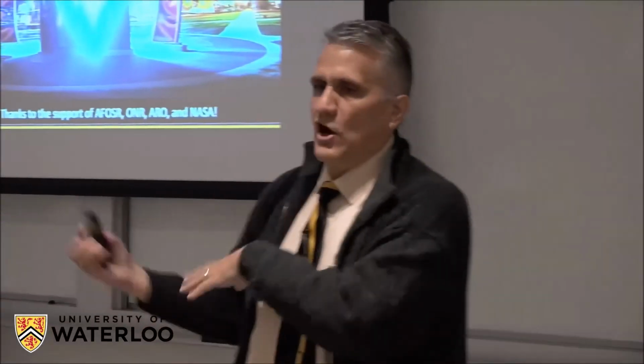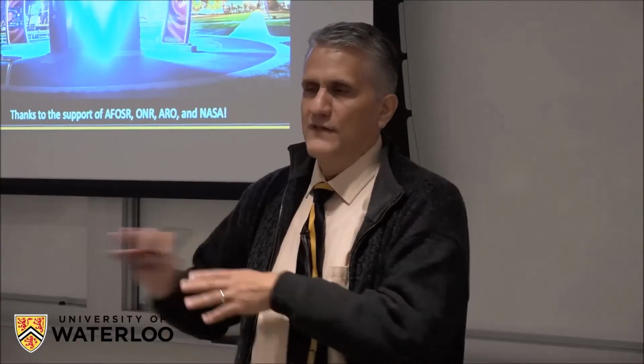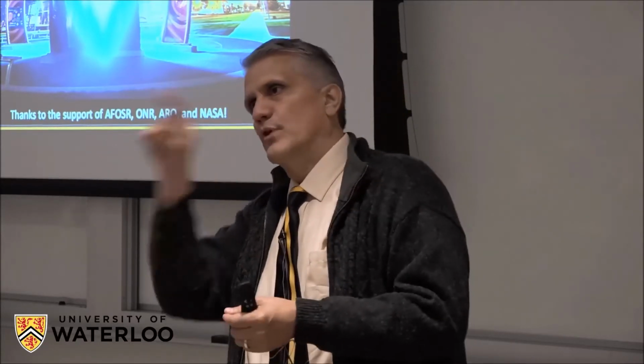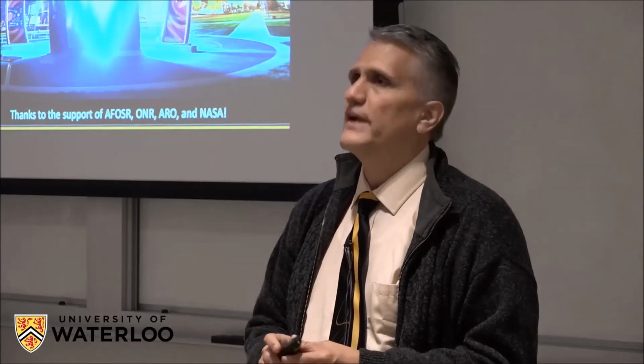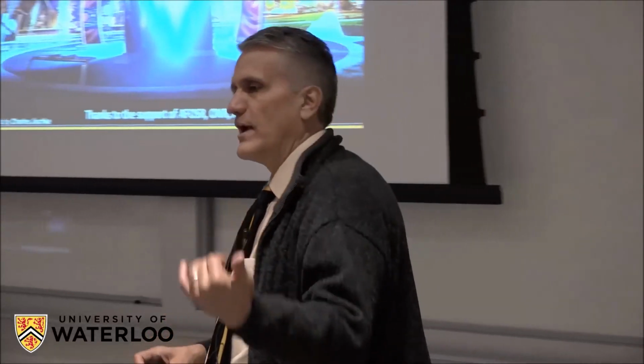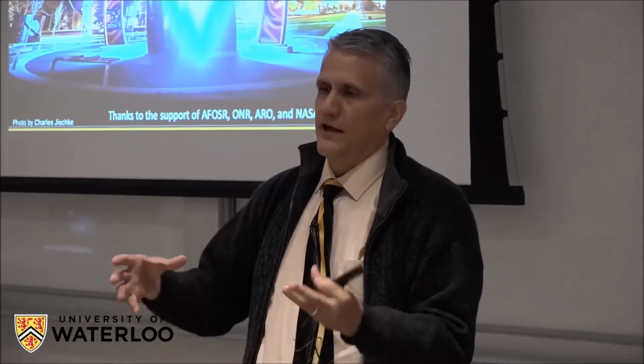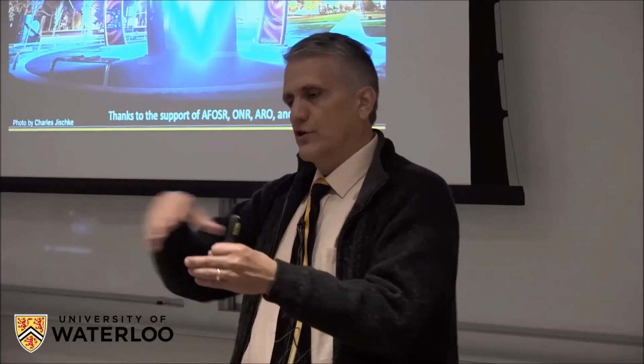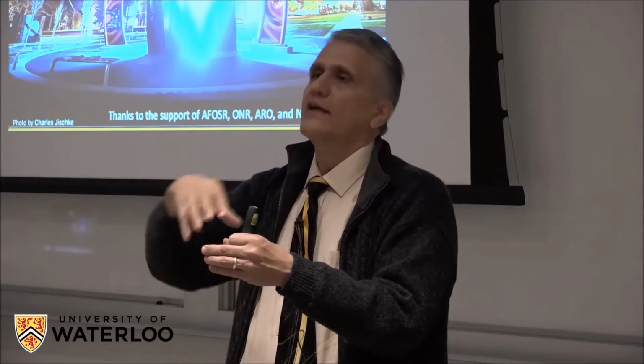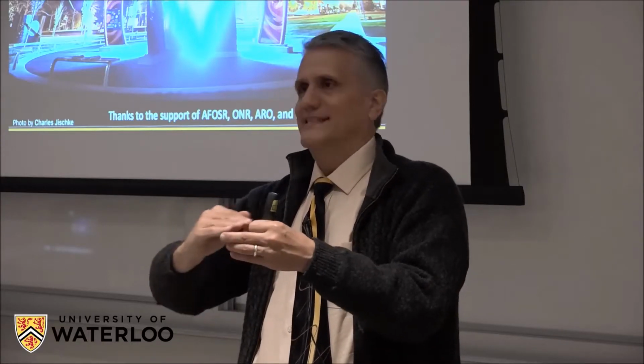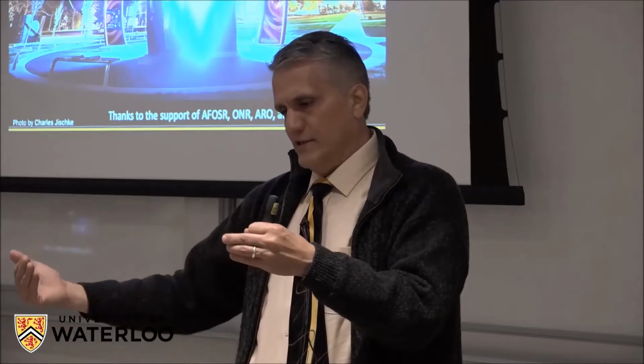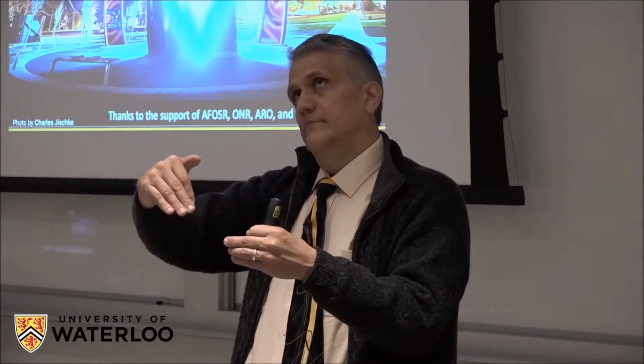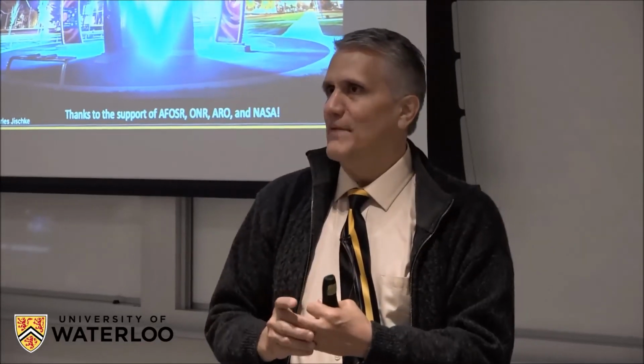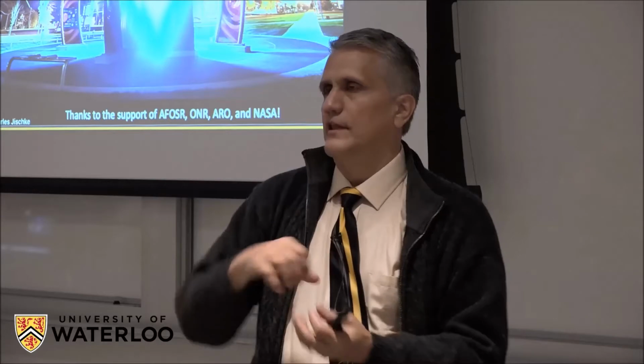For the FDM, my colleagues actually published a paper recently on not even energetic, but just FDM, and came up with all sorts of mechanical testing quantifying, if you print different orientations, how does it affect the strength? So that's a real key issue that we need to look at. But there are ways. I was just this week talking to a colleague. For UV cure, you put the polymer down, and then you apply UV light, and that cross-links the polymer, and it makes that interface, which could be very problematic. I think he was saying you take an ionized gas and open up those links. So what I think going forward might be good to minimize those problems is to do that to improve the layer-to-layer adhesion.